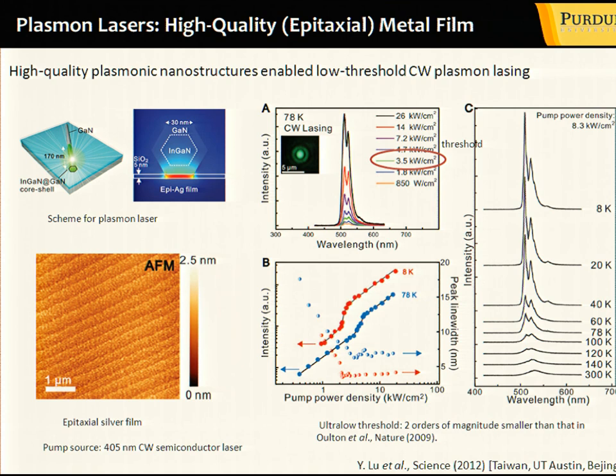Coming back to the gap surface plasmon nanolaser, this is recent work which comes from a group from Taiwan, University of Texas at Austin, and Beijing. They use a similar structure to what Shang Zhen's group in Berkeley did, but they replaced the silver plate with epitaxially grown silver. I will speak about materials quite a bit during my presentation, because this is really what I believe is critical for the field: to improve the material components which we use to build these devices. And by using this epitaxial silver, which has smaller losses, they were able to decrease the threshold by two orders of magnitude, so that lasing was possible in the CW regime, although still at cryogenic temperatures.